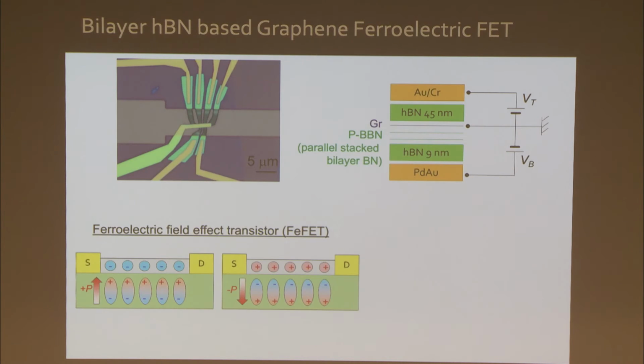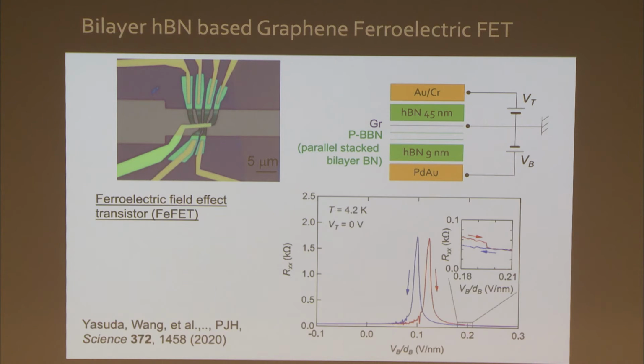So we fabricated a parallel stack bilayer boron nitride. It is an insulator. So in my group, since we do electronic transport, what we did to check the state of the ferroelectric is we slap on top graphene. We then put dual gates, bottom and top gates, and then we make a ferroelectric field effect transistor, where the resistance of the graphene is going to depend on the polarization of the ferroelectric. Okay? So with this, we measure the resistance as a function of the electric field, which we can control with this dual gate geometry. Okay?